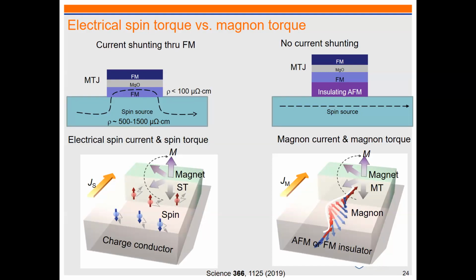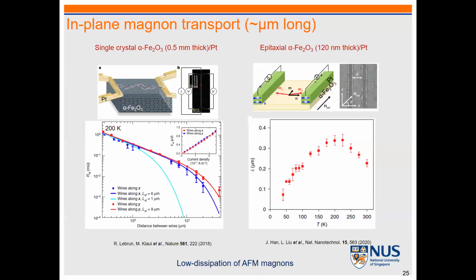with this large resistivity. So then we thought maybe we should just put an insulator here. Then nothing will go up. Then the problem is how you are going to move your accumulated spin into your magnet. So the idea is maybe this insulator is an anti-ferromagnetic insulator. It's magnetic but anti-ferromagnetic, and it supports magnons. So then this accumulated spin can change to magnon current and propagate, and probably we can make switching in this experiment. So that's the idea. In our structure, we try to use nickel oxide.